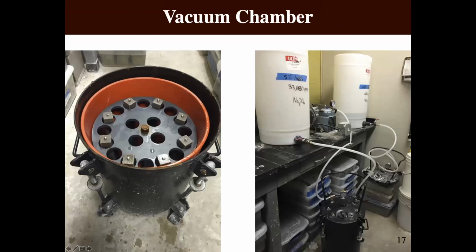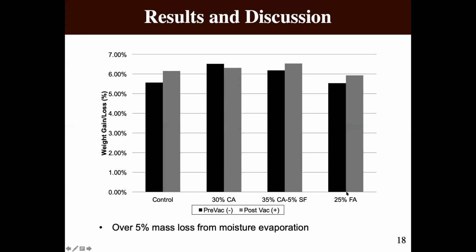These are some quick images of the testing itself. You can see the tanks that we use, the mortar bars that are placed in there, and the system in which the tanks are simply filled with sodium sulfate. Once the tanks are allowed to completely remove all the air, then we allow the sodium sulfate to begin draining into the bars. Again, prior to that, we have to dry the samples.